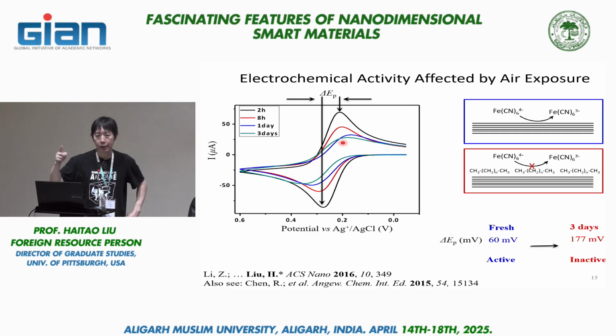If you think about all the electrochemistry you have learned, the oxidation and reduction peaks should be separated by 59 millivolts ideally. If the redox is reversible, that would be the number you are expecting. And we are getting 60, so that's pretty close. But we only get 60 if we do the measurement right away. If we do the measurement within 2 hours, you see pretty significant, obvious oxidation and reduction peaks in the CV, and that is a good indication that the redox reaction is reversible and fast.